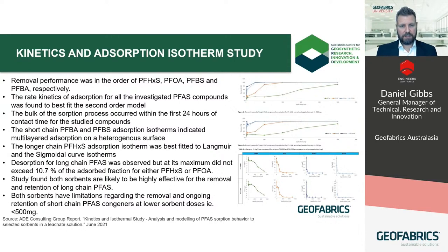So just summarizing the results, the removal order was PFHxS followed by PFOA, which you'd expect as there was less of these two longer chains in terms of their concentration in the original leachate. And we know that the longer chains are more readily trapped and are generally less mobile than the shorter chains. This was followed by PFBS and then PFBA, which also supports other research showing the higher mobility of PFBA and some other short-chain carboxylates over the sulfonates. The bulk of the sorption occurred within 24 hours, and that's common for a powder, which is far shorter than what you'd practically need in a landfill setting, but perhaps it's ideal for leachate ponds, which have immediate exposure.